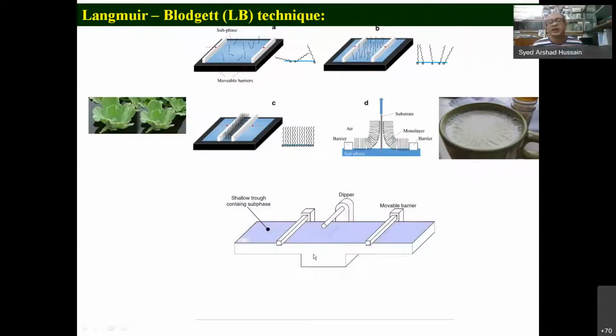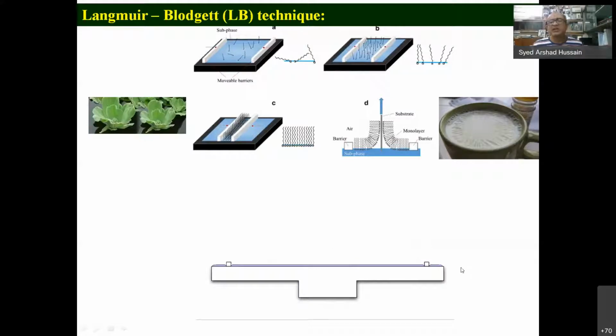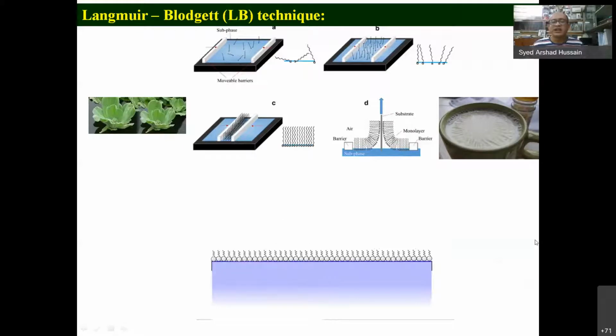In the machine, we have a trough filled up with some solvent. Normally, we use water. Then we spread the molecule on the surface, and mainly we make a solution in volatile, water insoluble solvents, say chloroform. Then we put the solution, the solvent evaporates, and the molecules float. Then a computer-controlled barrier can compress them like this. Then we deposit, say like this.